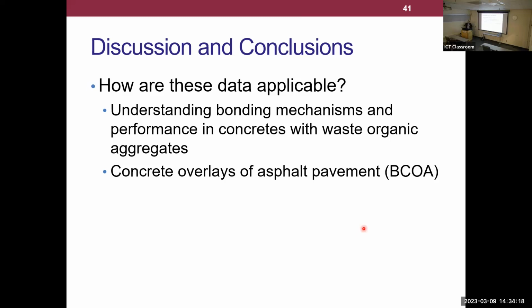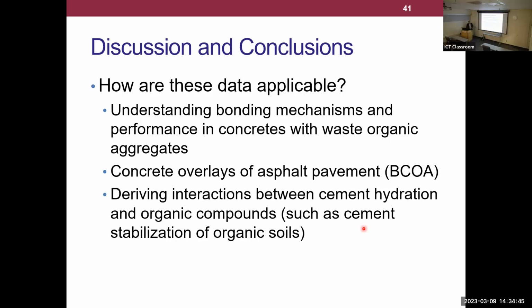So we're getting some mechanical interlock, as cement paste seeps into the porosity at the surface. And maybe that's our best benefit, because you're going to get an ITZ in that same scenario. We instead call it the OTZ, the overlay transition zone. Again, it's only tens of microns thick, but it's still there. So maybe we are getting this similar sort of behavior at that interface.